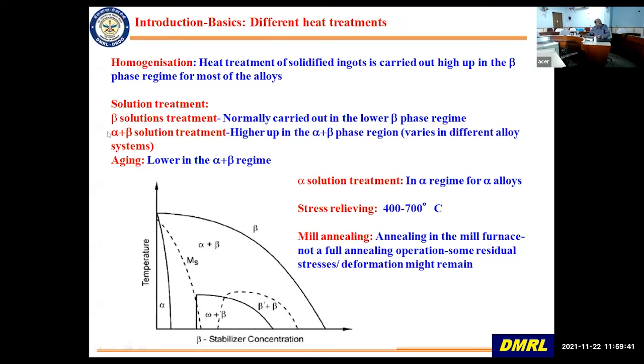Then as far as solution treatments are concerned, there are two solution treatments. One is beta solution treatment, which is normally carried out in the lower beta phase regime. And then there is also alpha plus beta solution treatment, which is carried out in the alpha plus beta regime. So beta solution treatment is carried out here, and alpha plus beta solution treatment is carried out here. Then you have aging, which is again carried out in the alpha plus beta regime, but lower down in temperature. Roughly in this regime, 500 and below. It can go up to 600, but it is normally lower temperatures. Then you have alpha solution treatment being carried out in alpha alloys, which is here.